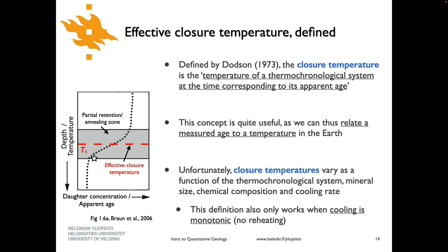And this is actually one of the somewhat controversial topics in thermochronology, because the way in which the tracks anneal is not fully understood. It's not like they just shrink from one end, but they can pinch closed in different places. The annealing behavior can make the data a bit challenging to interpret, especially in really old rocks. The fission track dates from Finland are quite controversial because there are questions about over 700 million years, how stable is a fission track at surface temperatures? It could be that they're annealing extremely slowly, but they could still be annealing even at low temperatures. So it's a bit complicated.